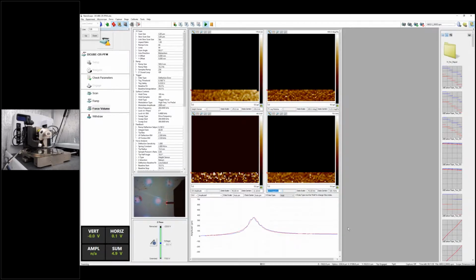So as you can see, when we do the scanning, we of course have the topography image of the sample. For the time concern, I only scan it at a relatively low resolution, which is 64 points per line and 64 lines per image. But still, we can see some grains because within this 5 micron range, these grains are relatively big. So even if I have a relatively large pixel size, I can still resolve these grains. And from the amplitude channel, we can see that at each grain or at different locations of this sample, the piezo response is also slightly different, which we also mentioned earlier. It's not uniform, right? And also the frequency channel, you didn't see a big frequency change, but if you look into the scale here, it's about 70 kilohertz.